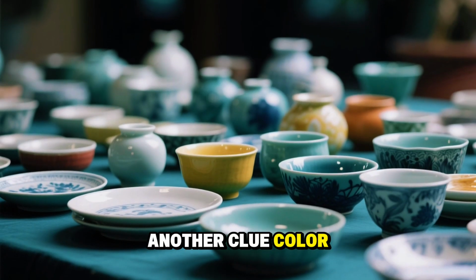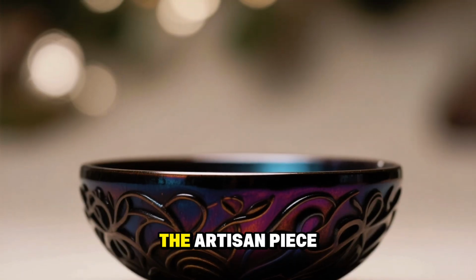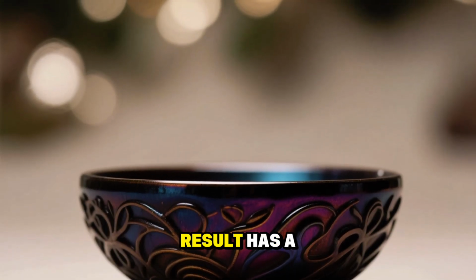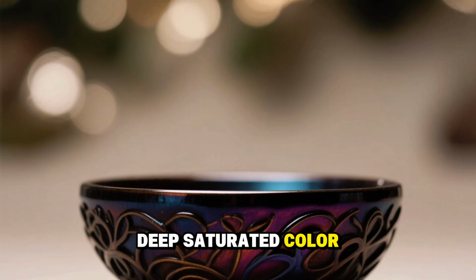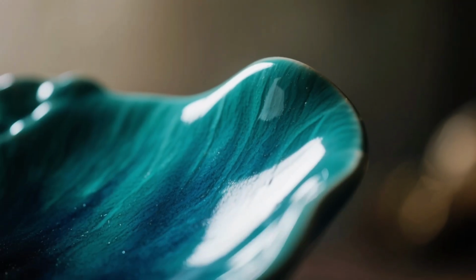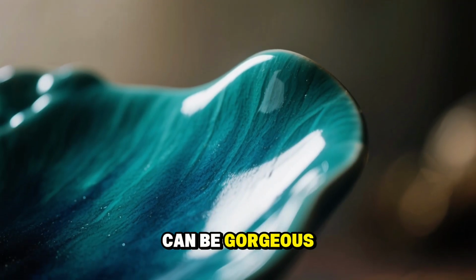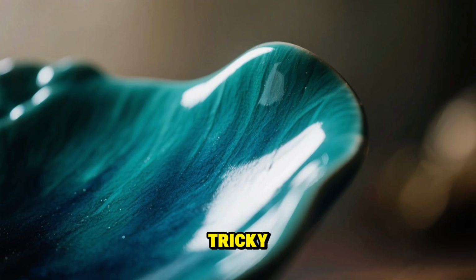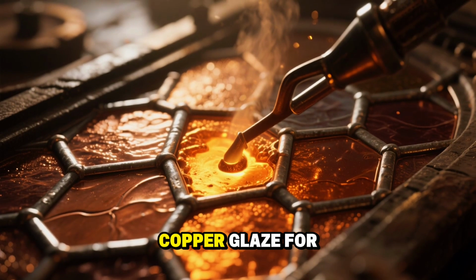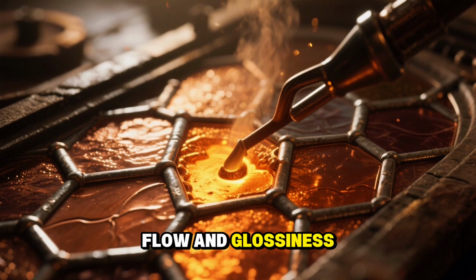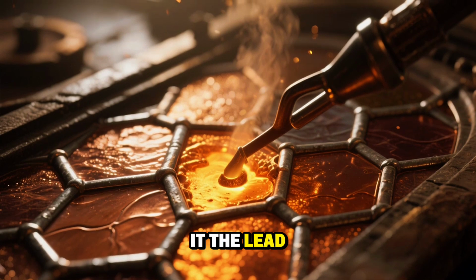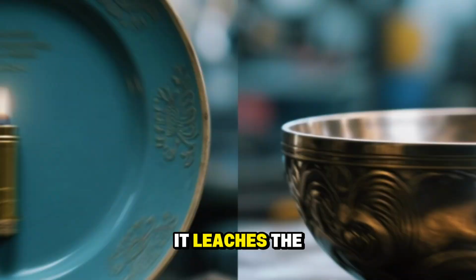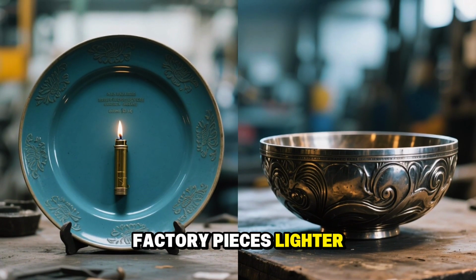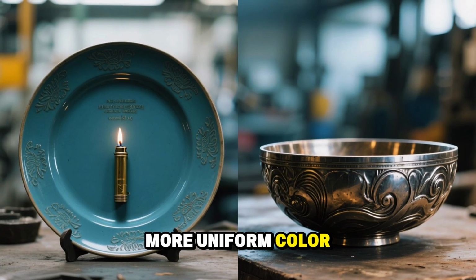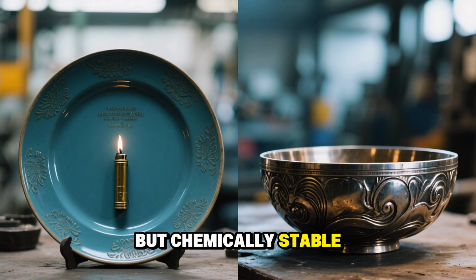Another clue? Color intensity. The artisan piece with the worst result has a deep, saturated color, rich blue-green. Copper-based glazes can be gorgeous, but they're also tricky. If you add lead to a copper glaze for flow and glossiness, and you underfire it, the lead doesn't bind. It leaches. The factory pieces: lighter, more uniform color. Less dramatic, but chemically stable.